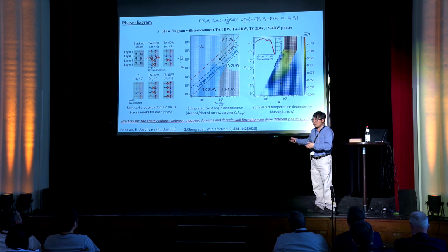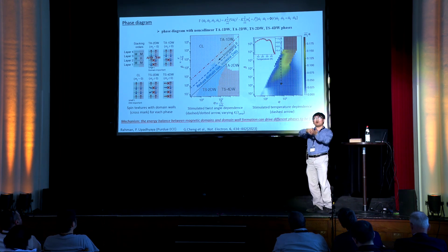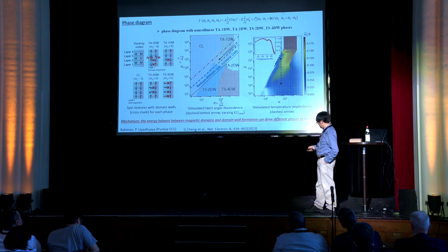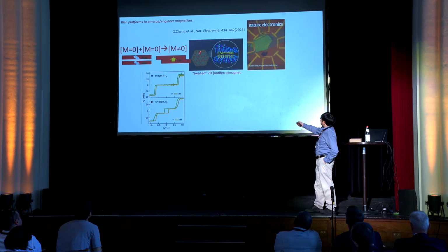So there are different phases that exist in this phase diagram. When you change temperature or voltage, you can actually traverse between different phases that can create a phenomenon like temporarily getting a stronger magnetization before it dies over. In fact, this is reproduced in the calculation. So I think this is a very interesting system.